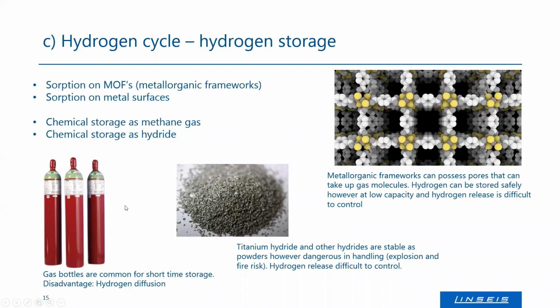Besides that, as said, storing it in bottles is usually achieved by pressing it in there. The difficulty with storing hydrogen in bottles is if it's just pressed in there, there's always micro leakage because hydrogen is a very small molecule. It can diffuse out of anything. So these gas bottles will always have some micro leakages, and therefore they have to be located outside of your building or in a room with a controlled air exchange. It has to be a vented room, and there's always a risk of burning, risk of fire, which is not so ideal. However, it's the easiest and most efficient way to store it at the moment.